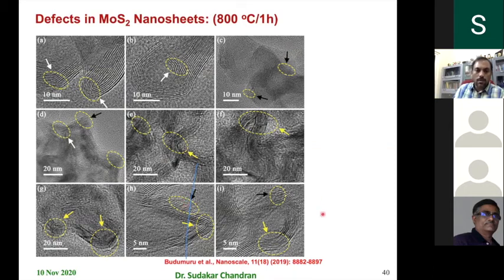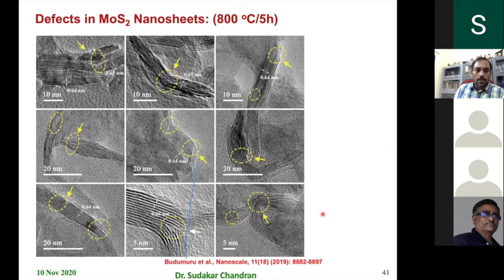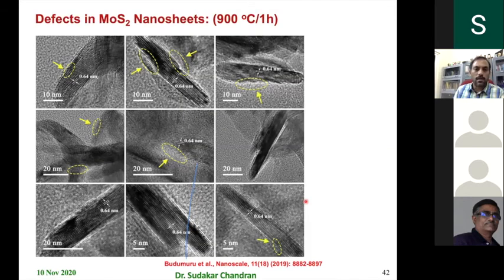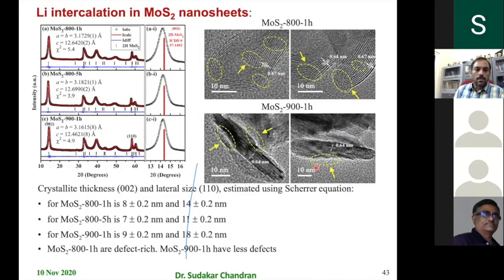So all these kinds of defects are there, and the concentration of this can be tailored by annealing at different temperatures and for different hours. In this one particular study, we took 800 1 hour, 800 5 hour, and 900 1 hour MoS2. As you can see, at 900 the crystals are already straight, so at least you don't have the bending and folding defects in large, but there are other defects still prevailing. So this influences the electrochemical property.